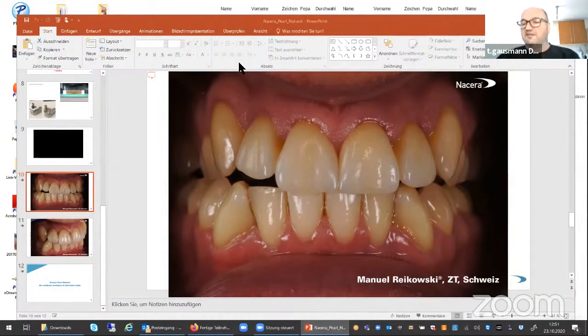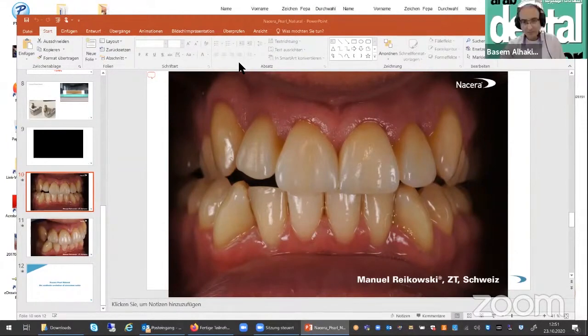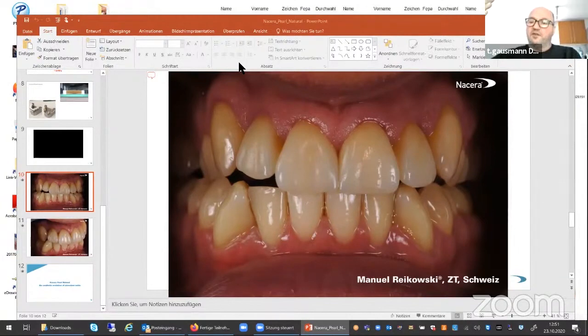And then my advice is always to sinter it standing, and the sinter support itself inside can be filled with crowns when you've got something in the correct color. But you have to take care that the sinter support is thinned out correctly. It can't be too thick. It must be a little bit thinned out.